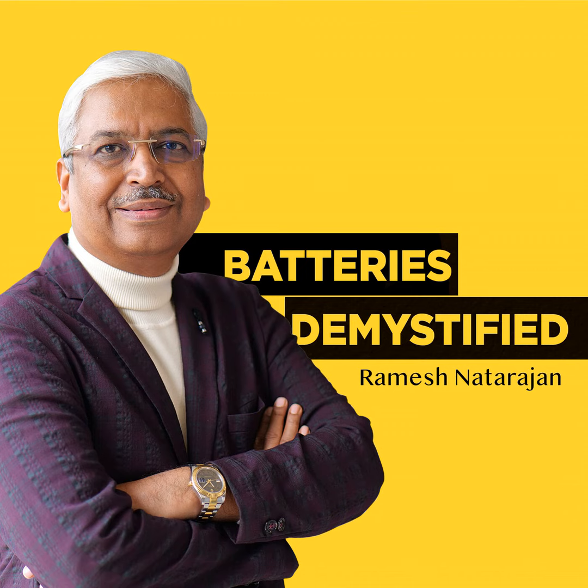Occasionally, it is noticed that both the positive and negative electrodes contain an adequate amount of active material, but there is a lack of electrolyte. Electrolyte deprivation is the cause of discharge termination in such instances. In such a circumstance, the battery designer focuses on optimizing the specific gravity of the electrolyte or increases the volume of the electrolyte if it is possible.